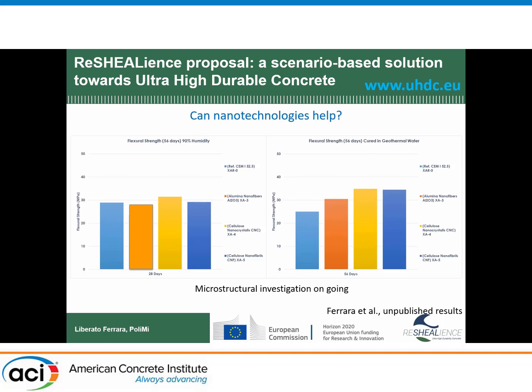So we tried to cure our material. We went to the tower. We brought big vessels of this sulfuric water. It's more or less the same one that we use in the spa, because it's not very aggressive. But the thing is that it contains a lot of sulfates. So we cured the specimen under that same water, and we got this. This is the reference material. And with the nano additions, we get a better strength.